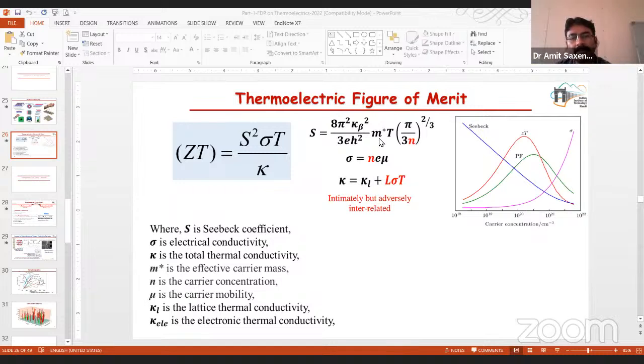Secondly, regarding mobility and the phonons, we know that in a solid, if we increase the temperature, phonon vibration will increase, and this decreases our mobility. And for thermal conductivity, we need good mobility, I think. If you are talking about the electronic part, you need the mobility, but we wanted to isolate the electronic part in the thermal conductivity.